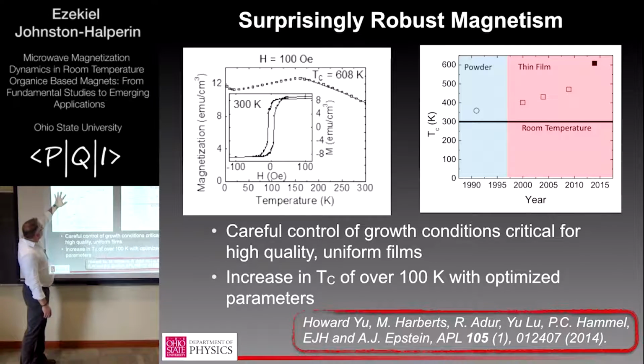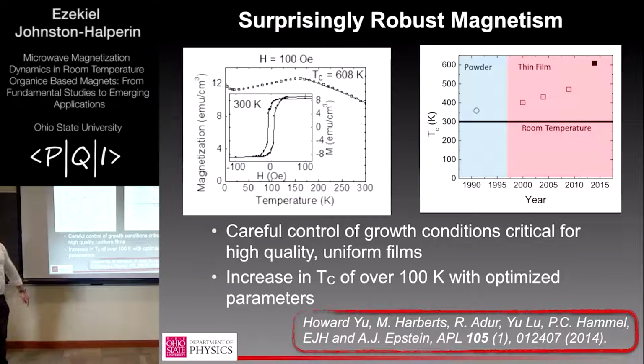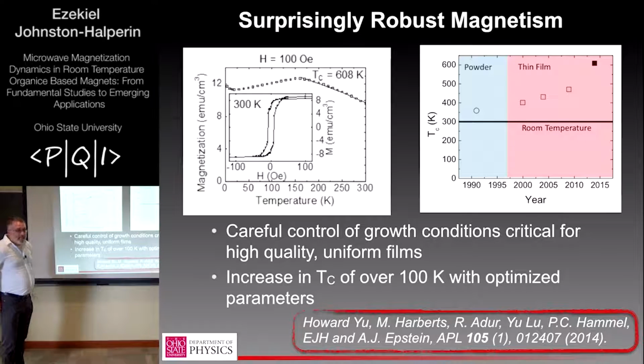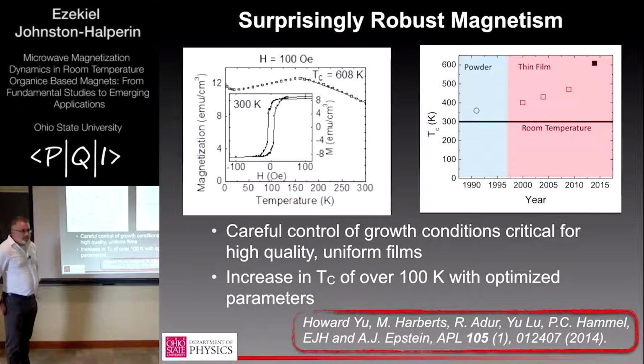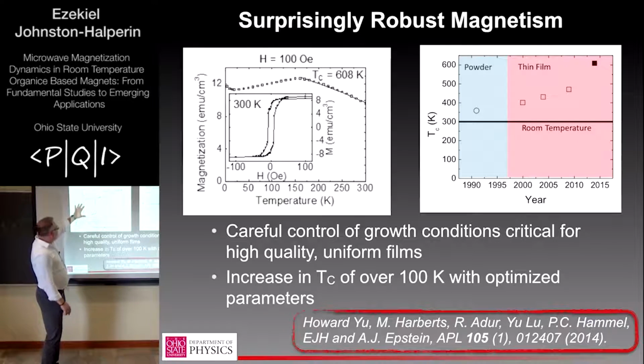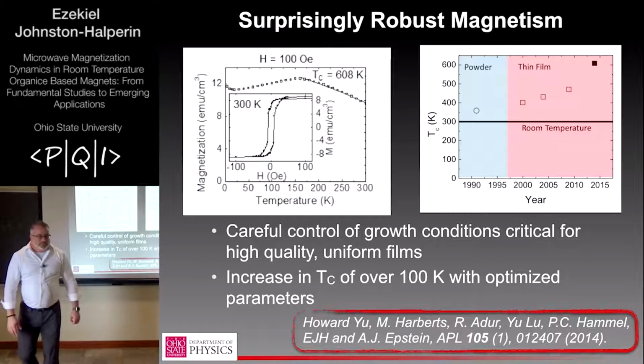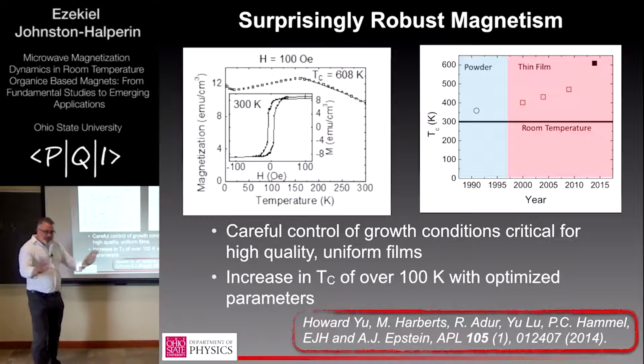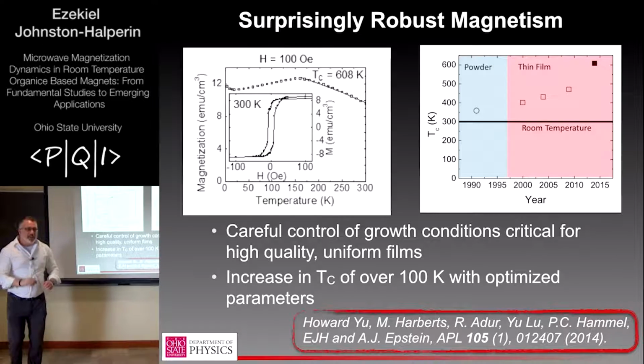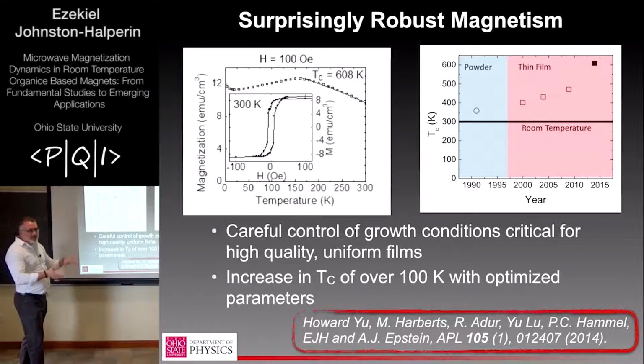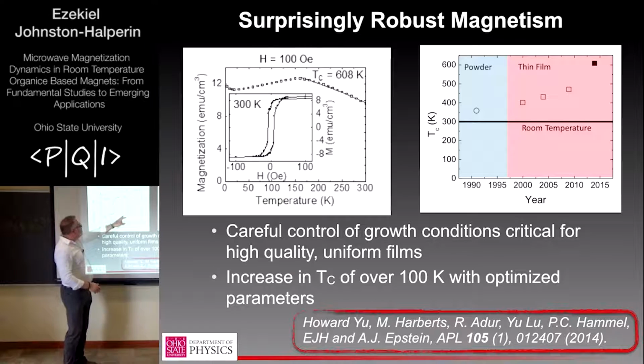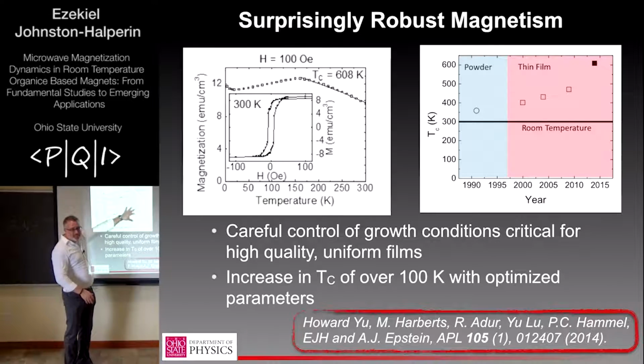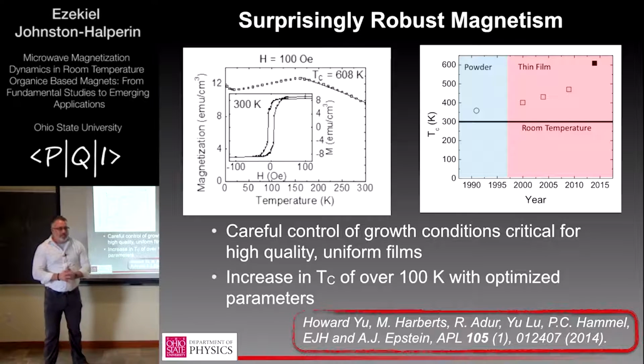Yeah, so I think this is probably dilute paramagnetic impurities in the film somewhere. At a guess. But you're measuring magnetization, not susceptibility. Well, it's in a finite field. Okay. It's in a 100 Gauss field. Yeah. I mean, it's very hard to measure just magnetization. Usually for a SQUID measurement, you apply a modest field to just get everything pointed in the same direction. So in this case, we want to measure at a field high enough that we're not seeing weird domain level effects in the temperature dependence. So we just want to be looking at the magnetization.